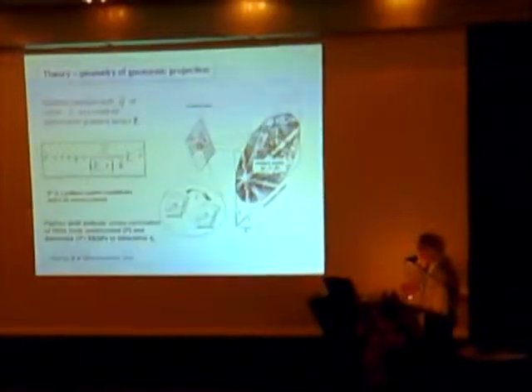And what you see, in fact, is the projection of a sphere onto a plane. And this is the gnomonic projection. What happens is that when you have a sample here, you can imagine a reference sample which is undistorted; any vector R will go to a point P. However, if you then deform this area, the vector R will go to R prime, which leads to P prime, and the shift from P to P prime we call Q.